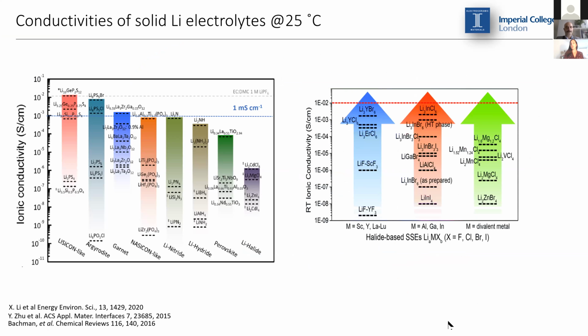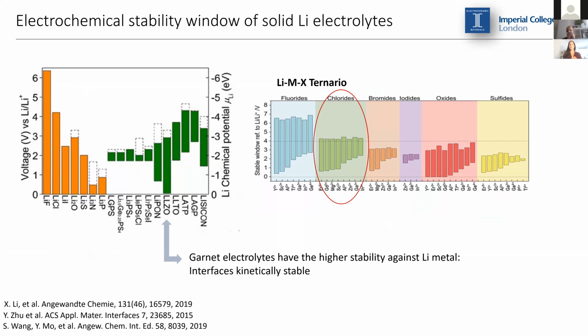In the last couple of years, another family of compounds has raised a lot of interest, and these are the halides. In particular, the lithium chlorides have been produced with very high lithium conductivities. As I said before, lithium conductivity is very important, but another important thing is the electrochemical stability window of the solid electrolytes. If we look at the sulfides, which were the electrolytes presenting higher lithium conductivities, you can see here that they have a very narrow electrochemical stability window, and therefore they are going to be very easily reduced and oxidized by the electrodes.